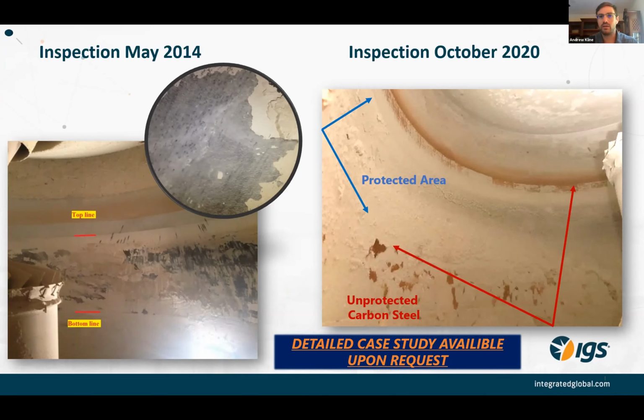Now we were able to get back in and inspect in October 2020. And during that inspection, we only had access from the access door. So we weren't actually able to get up to the spray affected zone where the coating was. But in this photo here, you can see that under the slag or any of the ash accumulation, there is no discoloration in that spray affected zone. And you can see almost clearly the lines of the coating on the top and the bottom. However, on the top and bottom around that zone where there is no coating, you can see the carbon steel has started to turn and is showing signs of corrosion.